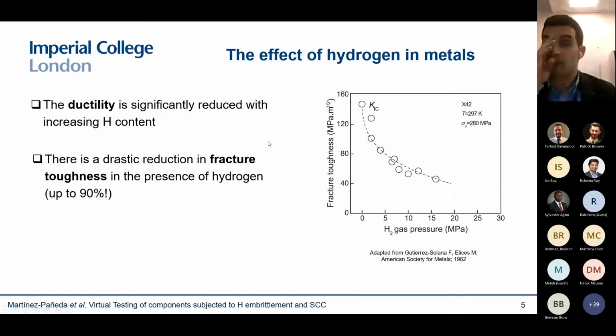Another effect is this drastic reduction that you see in fracture toughness whenever you expose your metallic samples to hydrogen. You can see an example here. So this is, I think, a steel that has a fracture toughness of 150 megapascals square root meter. And you can see that as you increase the hydrogen content, it fails at toughnesses below 40 megapascals square root meter. And this is for a low strength steel. In high strength steels, this reduction in the fracture resistance can be of up to 90%.